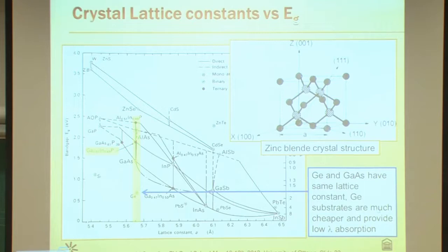These III-V materials have a crystal structure called zinc blende, and it's two interpenetrating FCC structures. Again, there are tetrahedrals, one gallium atom surrounded by four arsenic atoms. And when we grow epitaxially, you can actually grow on different plane orientations depending on how your substrate is cut. But most typically for solar cells, it's cut on the 001 plane, so you're growing vertically as shown here, just new layers on top of that. Growth modes.